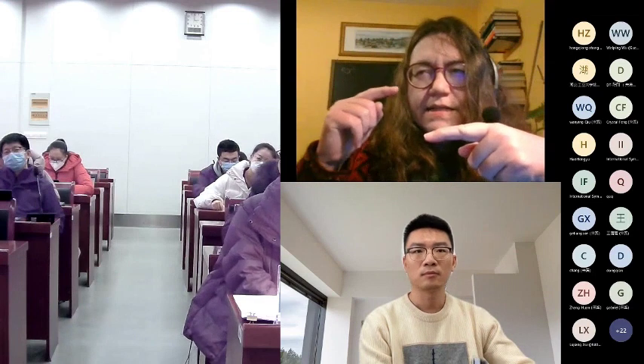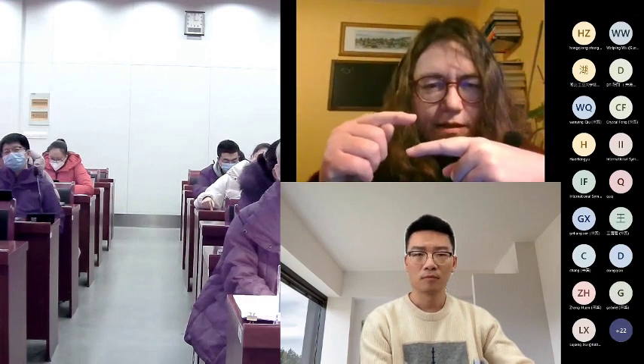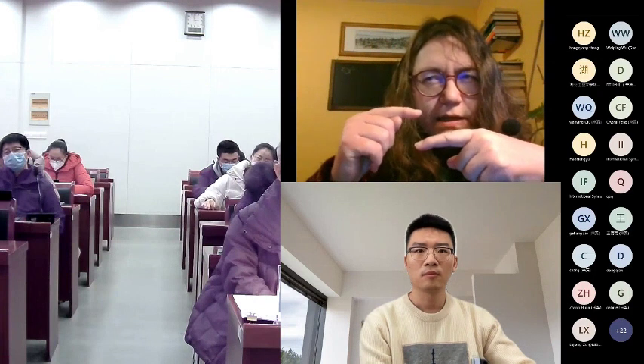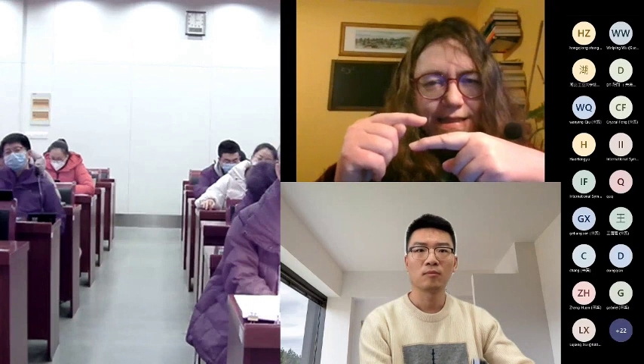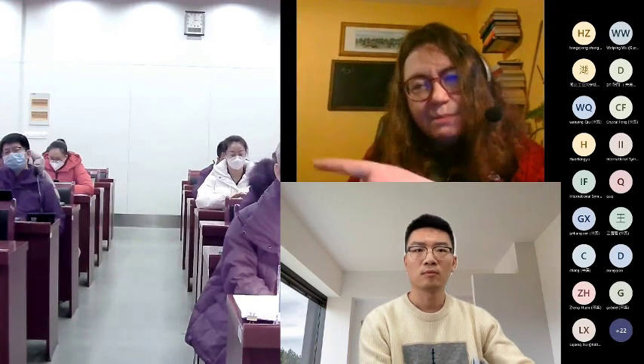The point is that after hydrothermal carbonization, the phosphate is nearly completely a solid, but a solid which can be leached or dissolved by acids. And then we can separate the phosphate from the hydrochar and precipitate it as struvite. I tell this because your process is a little bit different. You get it from the aqueous phase, but here it is first in the digestate, and in the hydrochar it's in the solid state, and then leached and precipitated.